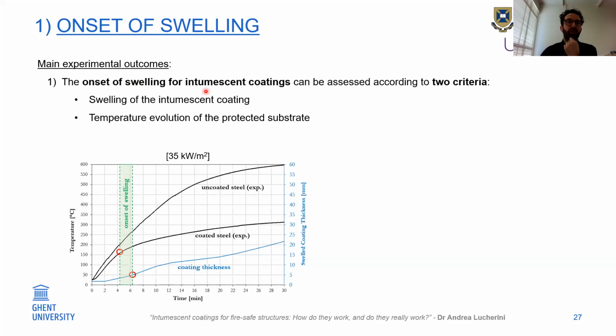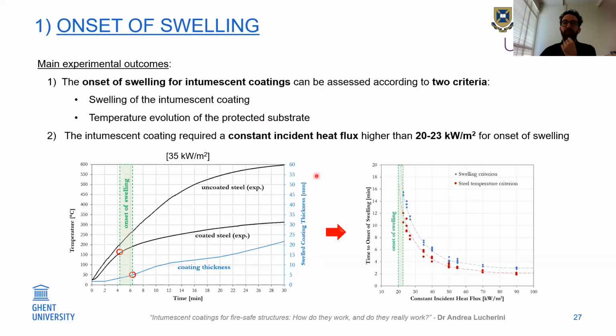I defined the onset of swelling according to 2 criteria. The first criterion, as I was showing now, was the temperature evolution of the protected substrate. The moment that this curve starts diverging from the uncoated steel, I define as the onset of swelling. I also quantify the onset of swelling as a minimum swelling, in this case 5 millimeters. So you can see that I define a certain range of onset of swelling for all the different experiments, and if I put them all together, I get a different time to onset of swelling at each constant incident flux applied.